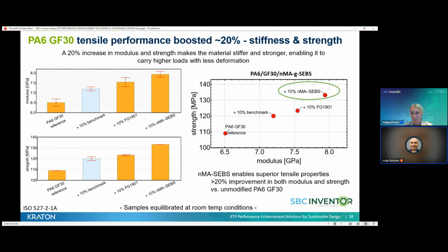We measured like this because these are in fact the conditions that the material will most likely see in application. If we have, for instance, an EV battery enclosure made with such a material, this enclosure is exposed to the environment, and after some time the properties of the material will tend to what you see here on the screen, fully equilibrated with the moisture content. Mm-hmm. Thank you, Luigi.